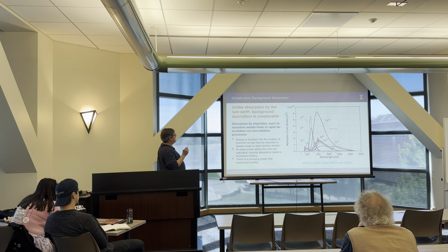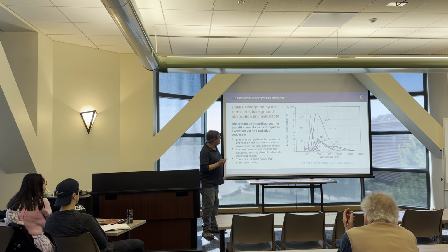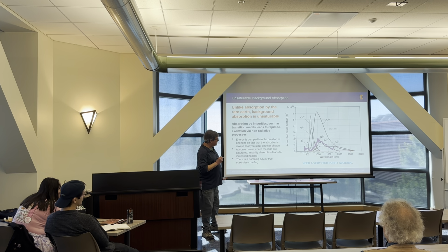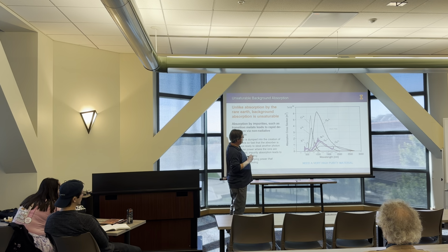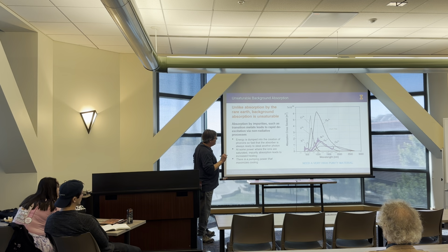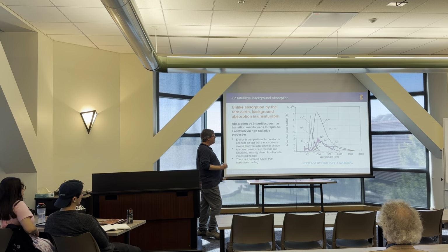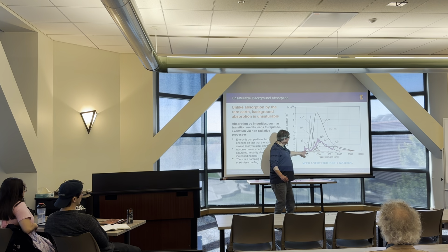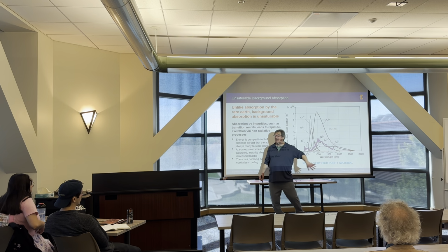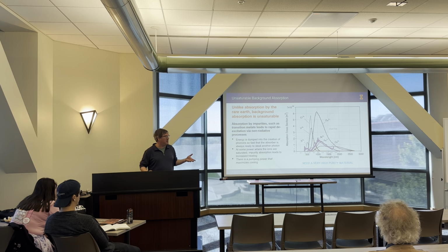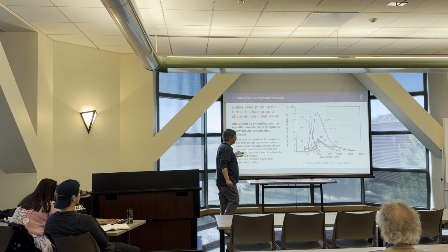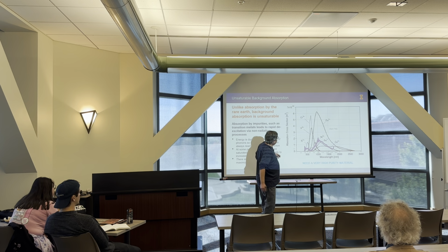The second limitation is unsaturable background absorption. Materials like ZBLAN and crystals normally have impurities, and the worst ones are transition metals: chromium, titanium, nickel, iron, cobalt. Apologies for the busy plot. They have broad emission spectra covering the visible to near infrared, including these ytterbium wavelengths that are interesting to us. Of course, if we were to operate at a wavelength outside of these bands, we wouldn't have to worry about these things, but ytterbium is nice because of its spectroscopy.